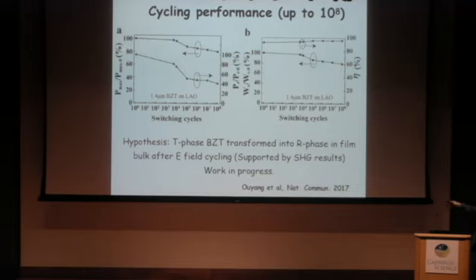So with this information, you can calculate the energy density change, and the efficiency. Efficiency actually slightly increases, more close to 100% after 100 million times cycling. And the energy density actually decreased about 20%. I think that's a very good record when you think about chemical supercapacitors. Usually they cannot cycle this many times. So the hypothesis here is the strain stabilized T phase, when cycled 100 million times, they transform to the more stable phase, R phase. So we have some more results which support our hypothesis.